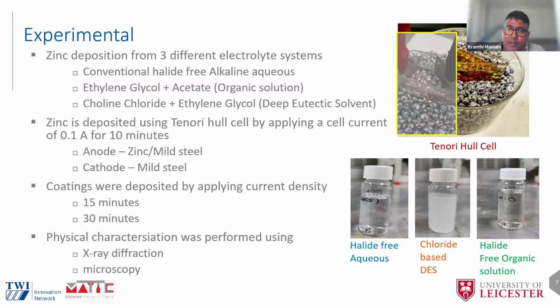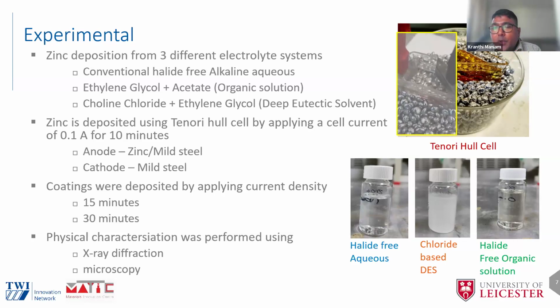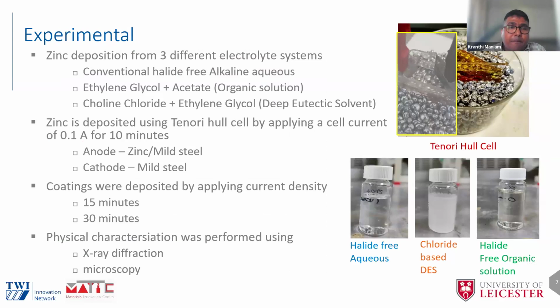And I would like to show a small video on how the plating happens when you apply a current of 0.1 amperes. You can see that the bubbles go near the surface, and that is how the plating happens. We used a conventional zinc anode, and the cathode was mild steel, because the main objective is to protect steel components.